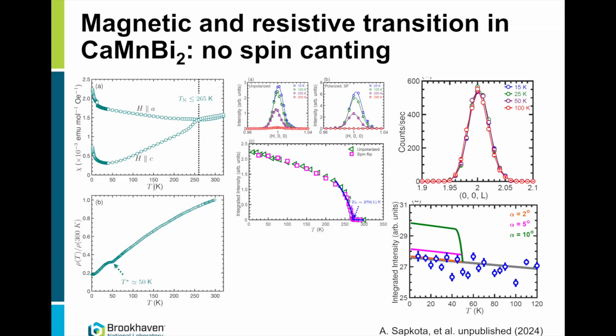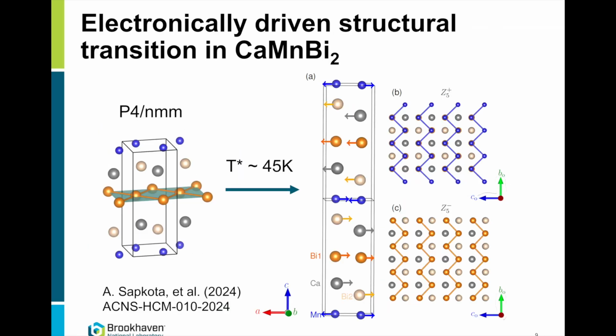So, as you cool it down, you have a lowering of your symmetry. You have this structural transition or charge density wave, if you like, with these zigzag chains emerging below like 45 Kelvin, right? Now, in ytterbium manganese diantimonide, the T star, the structural transition is roughly 800 Kelvin.